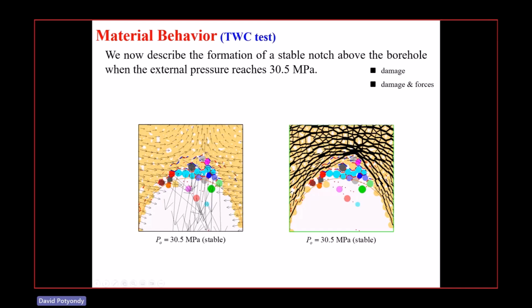What we're doing for this model is increasing the outer pressure from 30 MPa to 30.5, and you're going to watch how the material deforms in response to that and how it begins to form this breakout notch. So if we look at the damage, these colored things again are fragments that have formed.